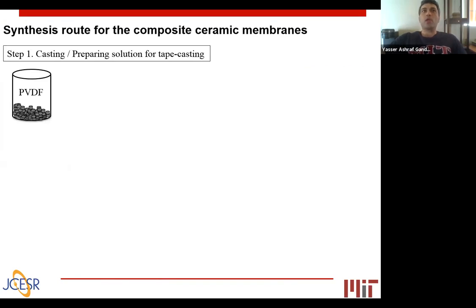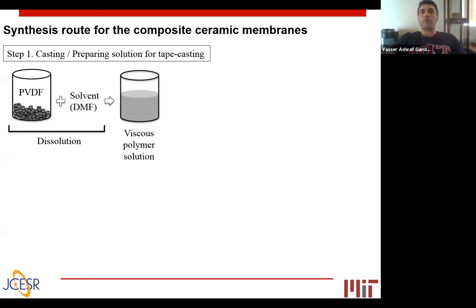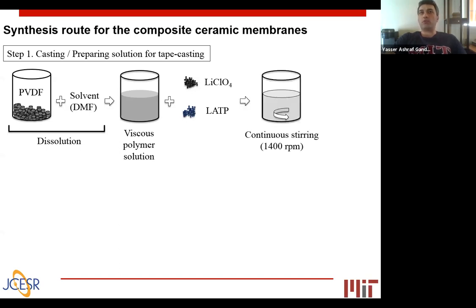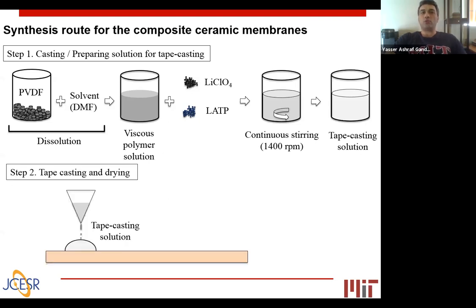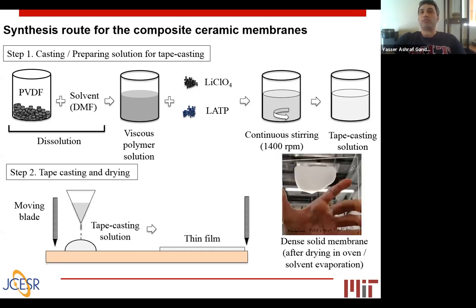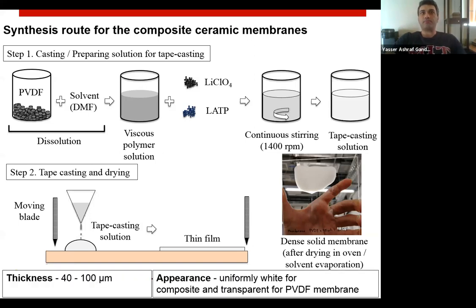To prepare the composite ceramic membranes, we took the PVDF powder and added the solvent DMF, and we prepared a viscous polymer solution, and then we added lithium perchlorate and LATP. After continuous stirring at 1400 RPM, we prepared the tape casting solution. Using the tape casting solution within the Dr. Blade apparatus, we can prepare the films, and then we dry them within the oven to prepare dense solid membranes. They have a solid white color, and we could tune the thickness between 40 to 100 microns.